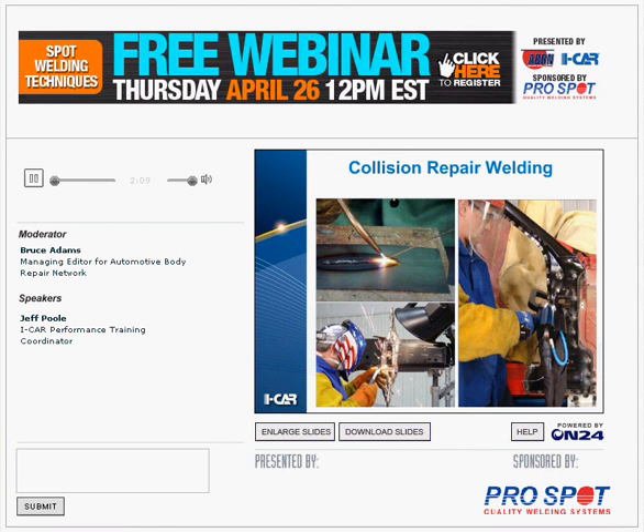The oxyacetylene welding process was accepted for a lot of years, and it was okay on the heavy gauge mild steels that we had at the time. But there was a lot of excessive heat there, and controlling that heat effect zone on these thinner steels, and the effects of that heat on the high strength steels, was really detrimental. So that was a major challenge for us. Around that same time, stick arc welding was the mainstay of anything that was heavy gauge, like on frames and things of that nature, and controlling that heat was rather challenging as well.